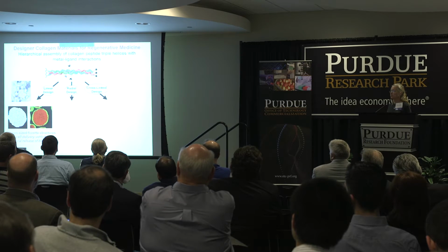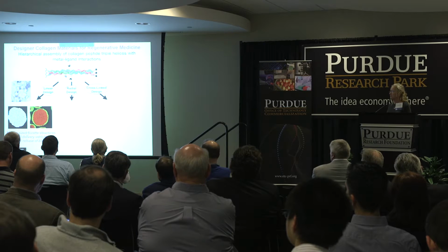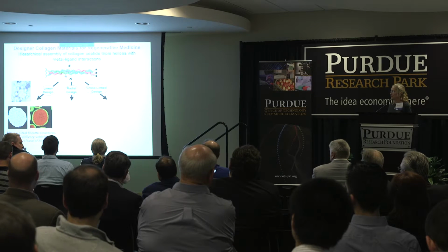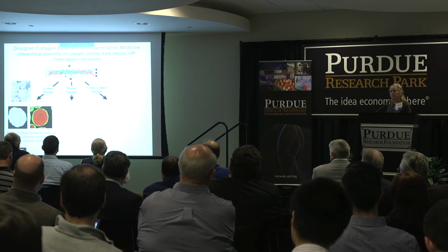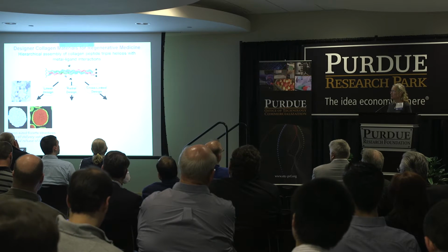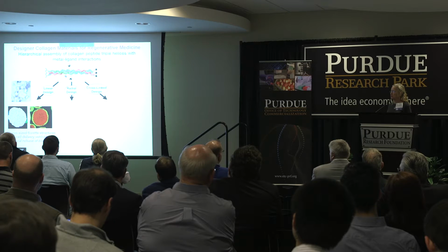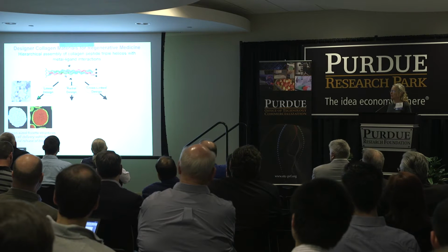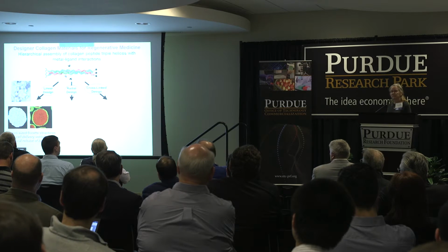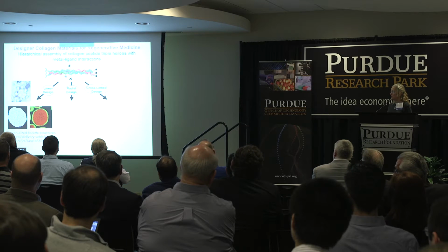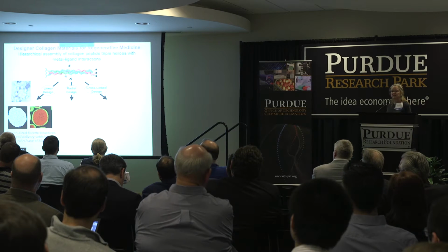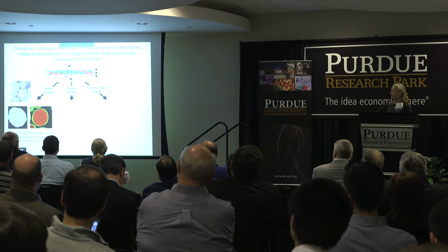highly ruffled microflorette structures that are at the micron level that we can decorate either on the interior or on the exterior with a variety of different biopolymers, including growth factors. And interestingly, because of the nanoscale morphology on the surface of these materials, they have a very good affinity for cell binding. So for instance, here's an image of these microflorettes interacting with a stem cell. And so we'd like to use these as stem cell delivery vehicles whereby we can have a temporal release of different biopolymers, such as growth factors.